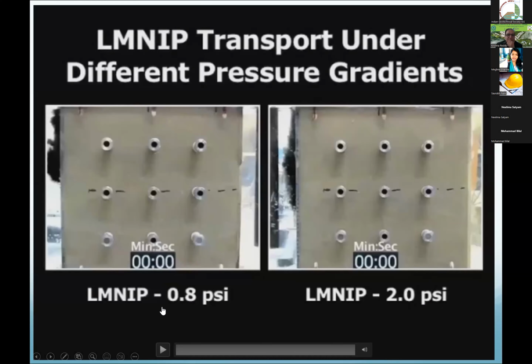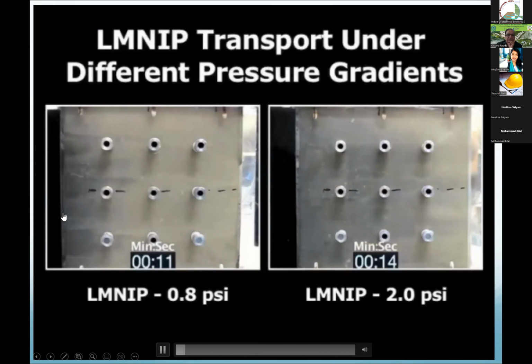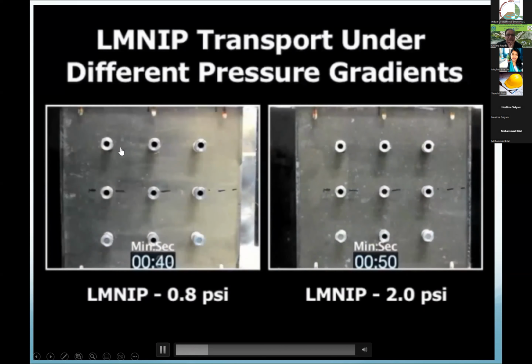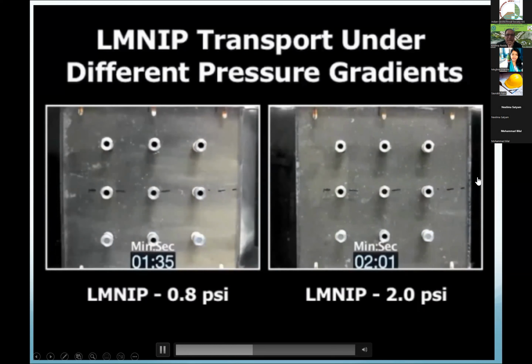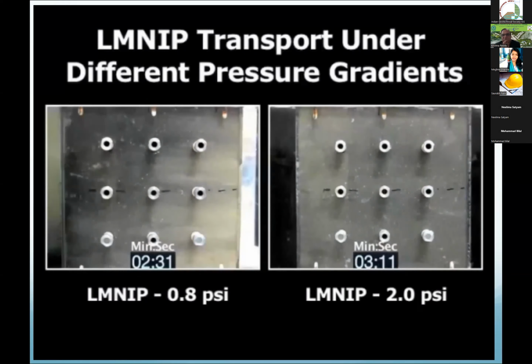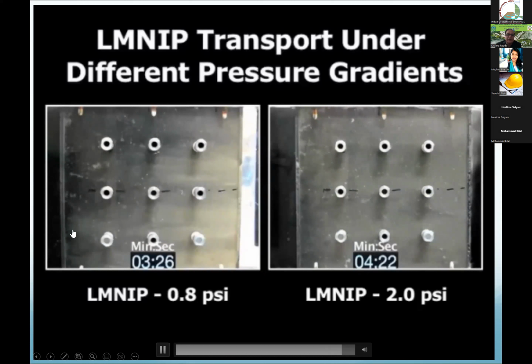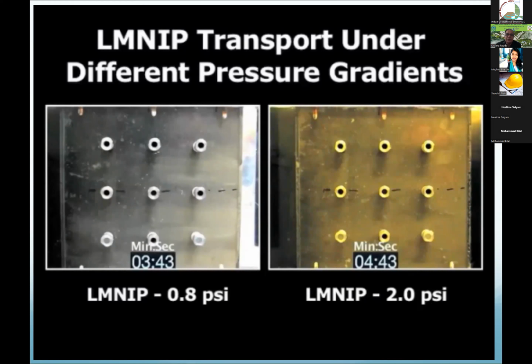Now let's look at the same things with modified nano iron particles. This is the lactate modified nano iron particles, right? There's a low pressure, the same low pressure and high pressure. Let's look at how this goes. Here I'm injecting the nano iron particles from this end. You can see the distribution of this one. See the color, right? The black color is more uniform, and you see something coming out at 2 psi. It rapidly passes through, and you see the color is pretty uniform. That shows that nano iron particles are uniformly distributed, right? The previous one you saw at 0.8 psi, you didn't see much transport, but here you can see a lot of transport. But higher pressure definitely flushes through this entire soil uniformly, and you can see nano iron coming out on the other end.